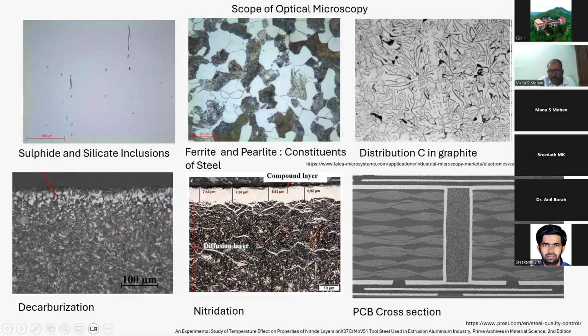Now you have the PCB cross section. These days, PCB people are interested in finding out the effectiveness of the solder. They want to understand to what extent the solder is effective in offering a conductive path, whether there is a break in the solder, or a delamination of the copper layer.